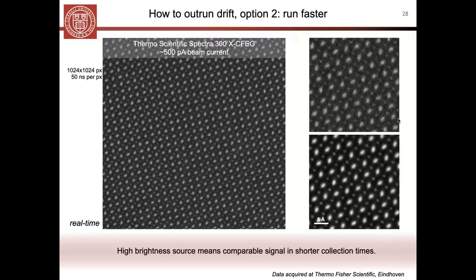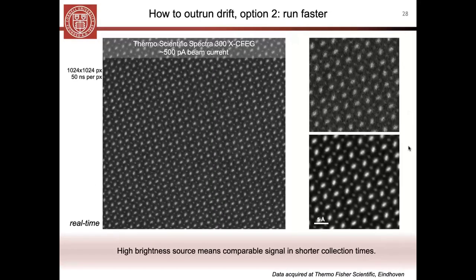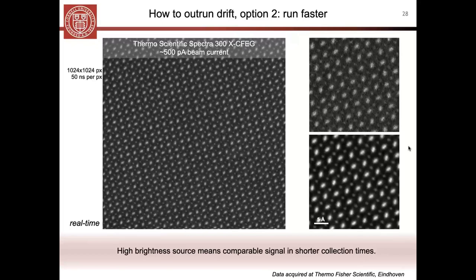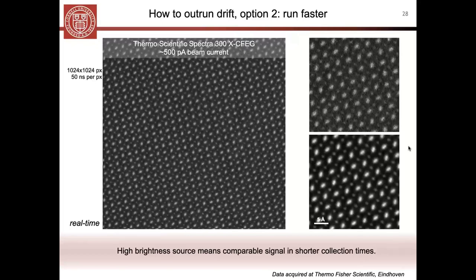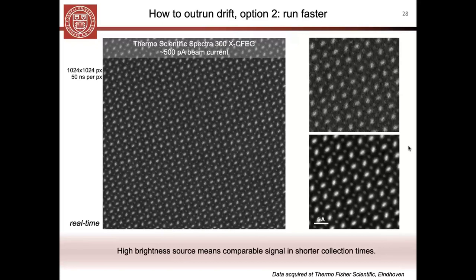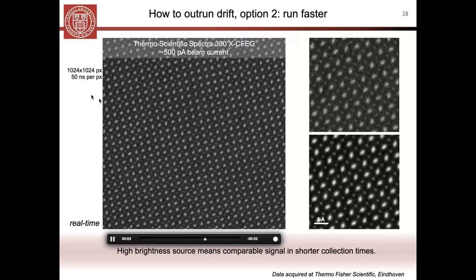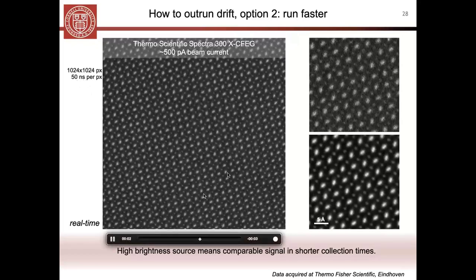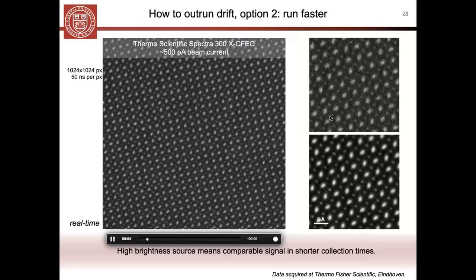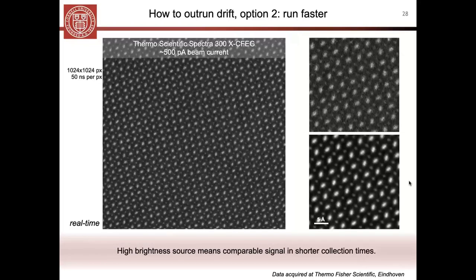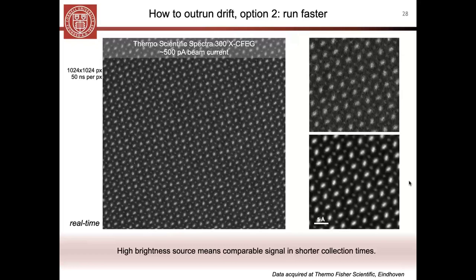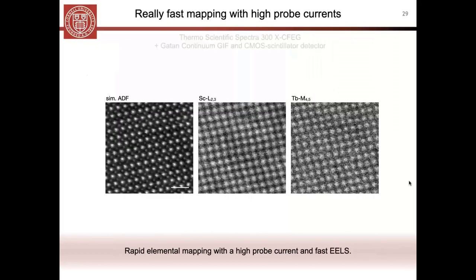Just to give you a visualization of this, you can think back to the first video that I showed you on the XFEG source. Now, instead of using 500 nanoseconds per pixel, or half a microsecond per pixel, I'm now using 50 nanoseconds per pixel. So with a factor of 10 increase in speed, you can see in a single frame that we still have very good signal to noise, and of course can register that into a very nice atomic resolution STEM image. And so for EELS, what does that set us up to do?